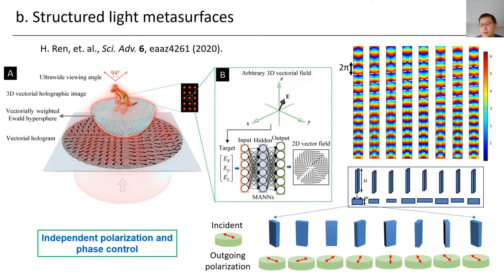Based on this motivation, we can develop metasurfaces with different aspect ratios in the in-plane directions as well as different heights, so that they can have different dynamic phases changing from 0 to 2 pi. These aspect ratio nanopillars have different dynamic phases, but simultaneously you can make them subwavelength half-wave plates, so that when you rotate these nanopillars, they give you different outgoing polarization states. Altogether, we can achieve independent polarization and phase.